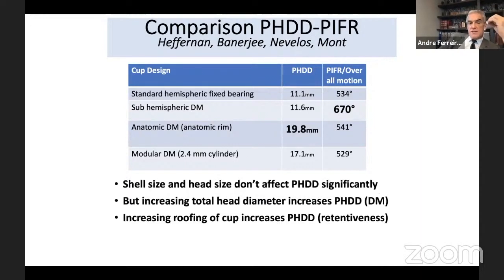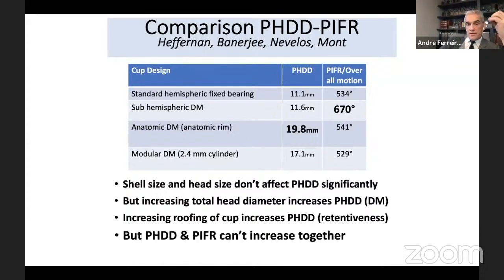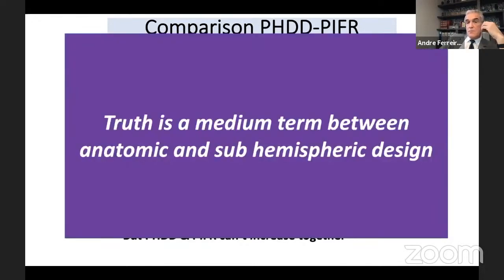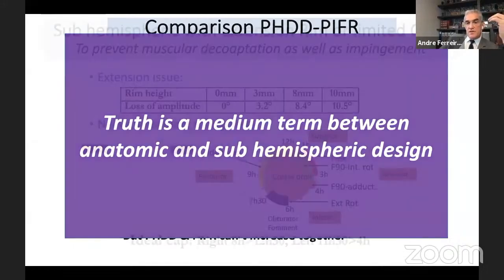So shell size and insert size don't affect PHDD significantly, but increasing total head diameter increases PHDD. That's the reason why durability is better, like Charnley and Wagner showed in the past. And increasing roofing of the cup increases PHDD. It is the retentiveness, the ability to keep the insert into the shell to avoid a classic dislocation. But PHDD and PIFR can't increase together. The truth is a medium term, of course, like in life, between anatomic and subhemispheric design.